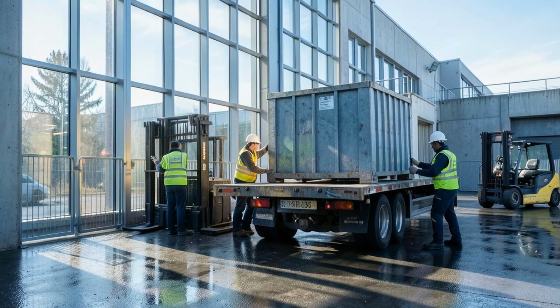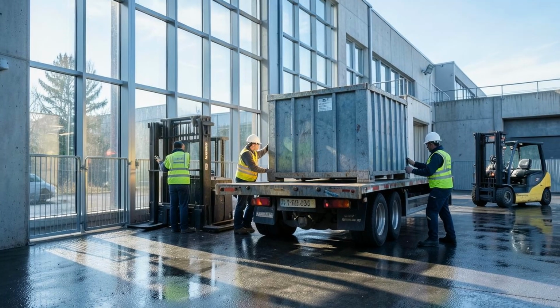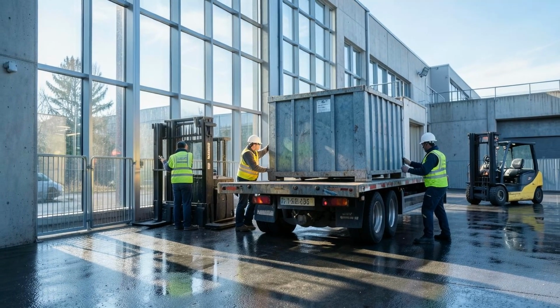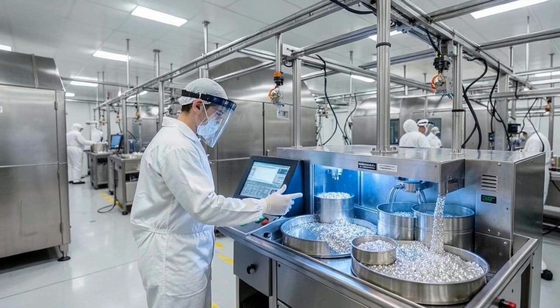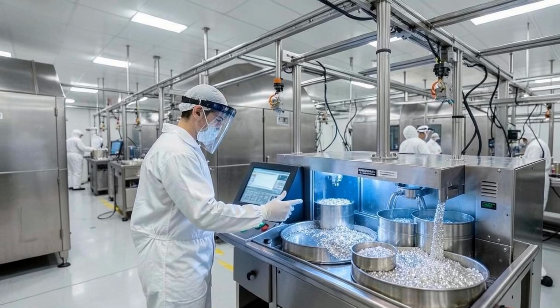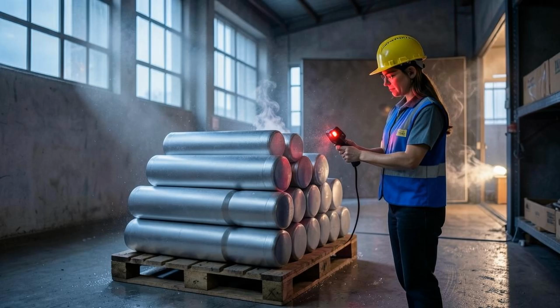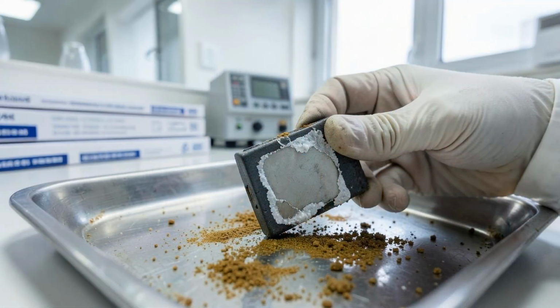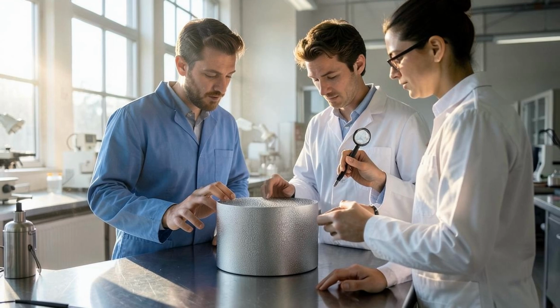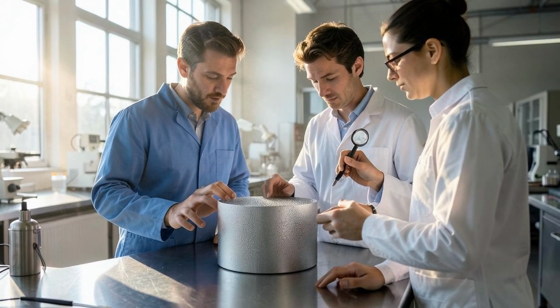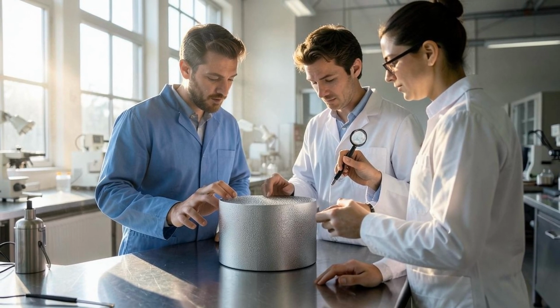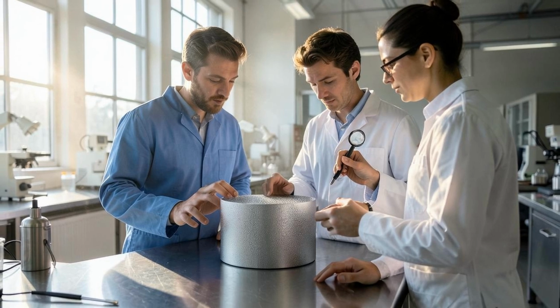For decades, magnesium batteries have been the dream for high-density storage without expensive metals like lithium or cobalt. The problem has always been the anode. When you try to use pure magnesium metal as the energy source inside a battery, it does not play nice with its surroundings. It degrades rapidly at room temperature and forms corrosive layers that kill the cell in hours rather than years. Tohoku University researchers engineered around this failure by creating a specific alloy compound known as Mg2Sn.